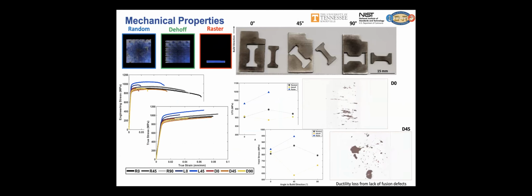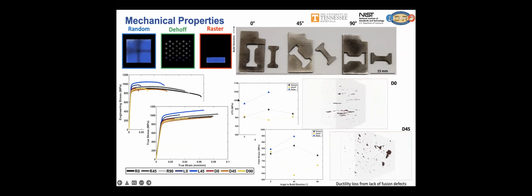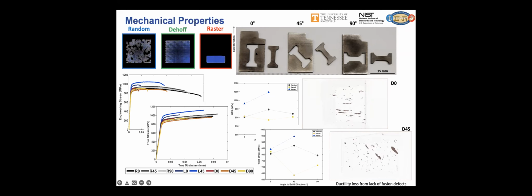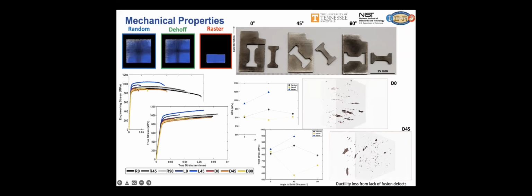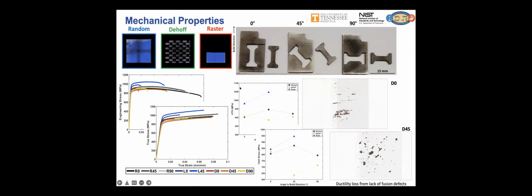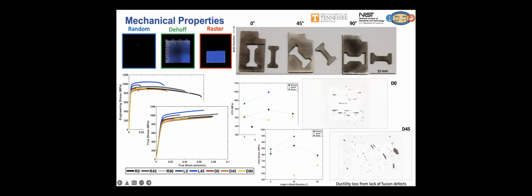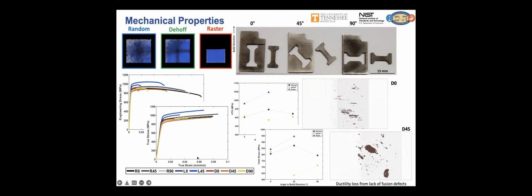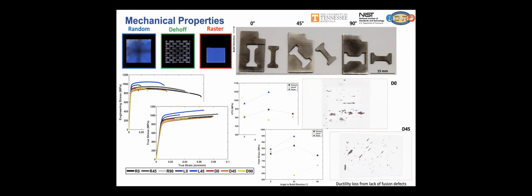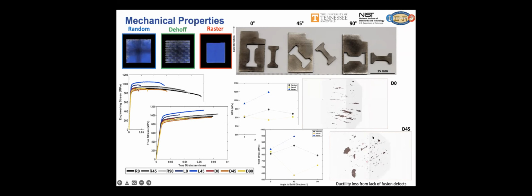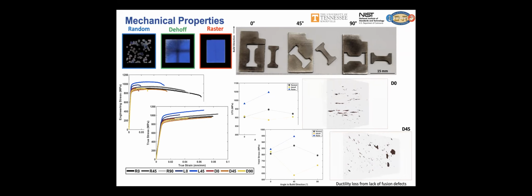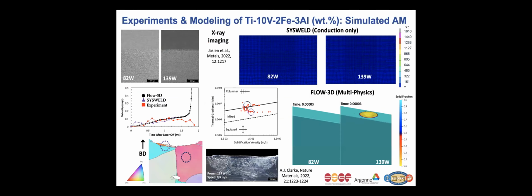So now that we're armed with all this nice crystallographic texture information from neutron and large scale EBSD, we want to start linking that to mechanical properties. So we pulled some mini tensils at 0, 45, and 90 degrees to the build. And here are some example mechanical property results that we've acquired. We're currently working with VTT in Finland and also Los Alamos National Lab to try to forward model with crystal plasticity the mechanical performance of these AM builds. We're also looking with computed tomography at the defects that we see and correlating that again to the mechanical properties as well. So this is an active ongoing area for us.